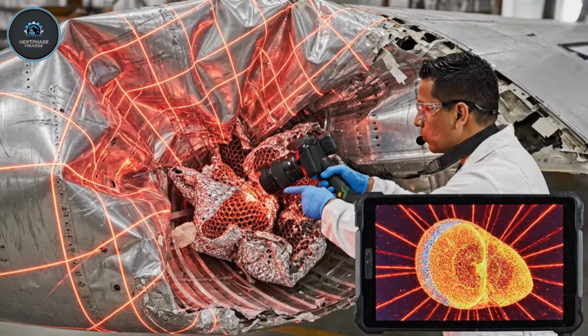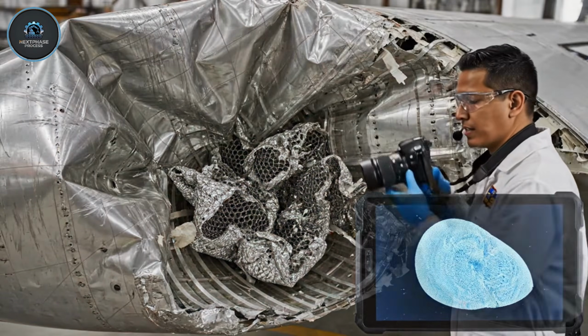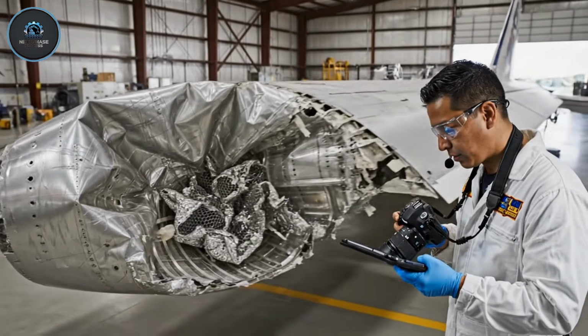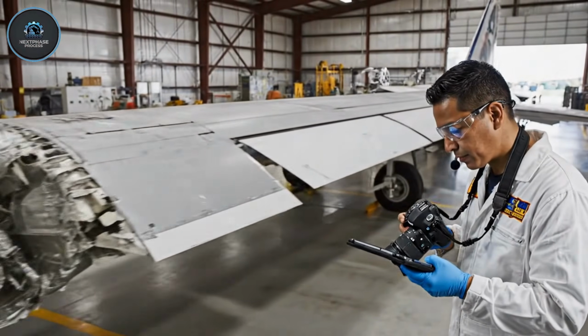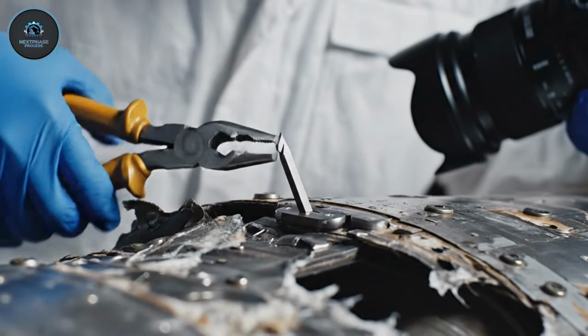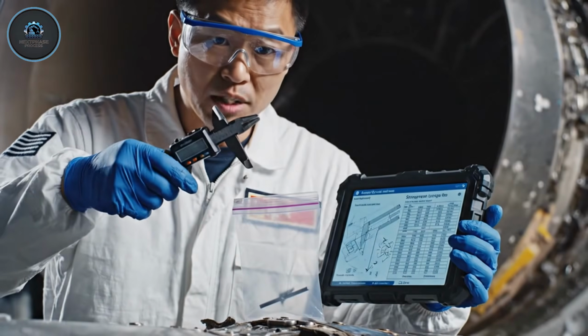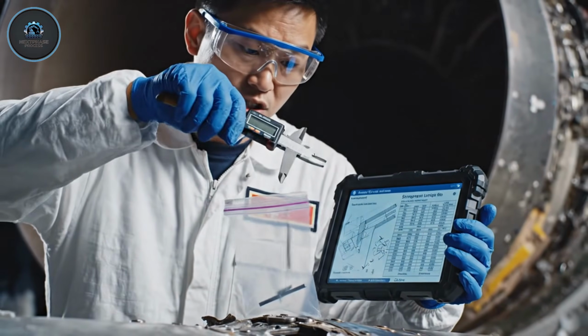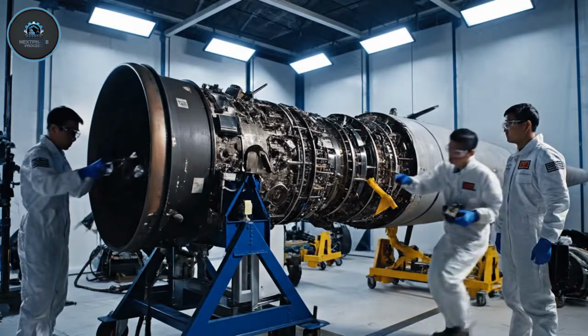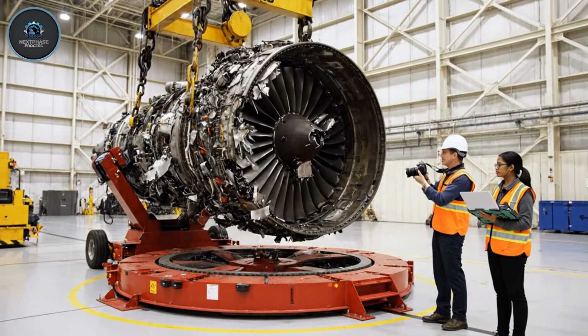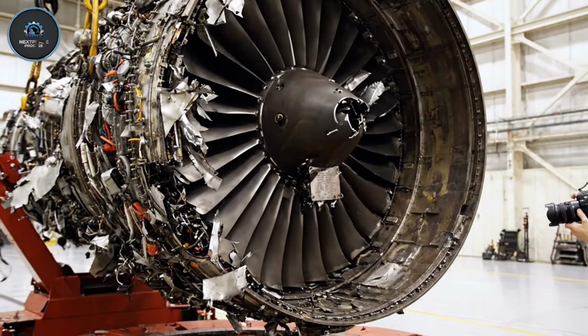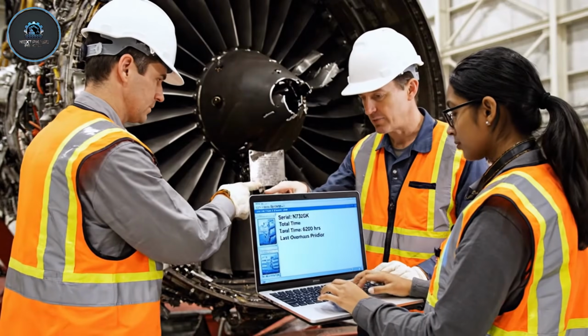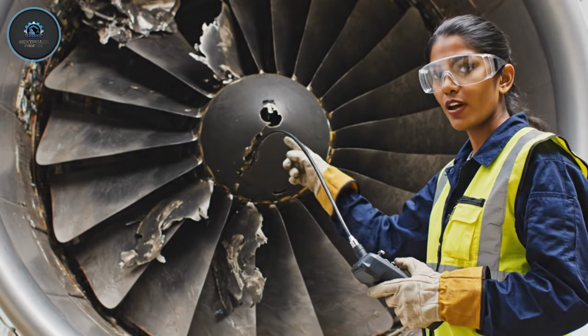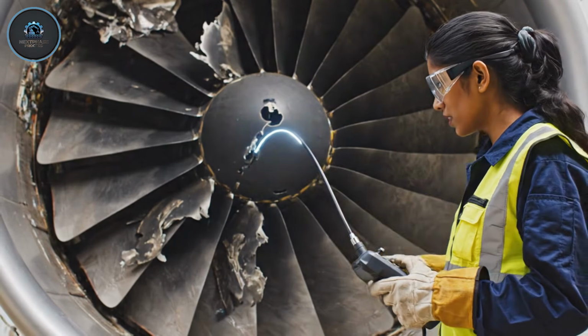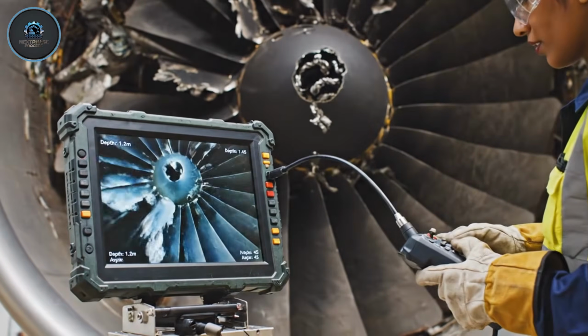Maximum crush depth 42 centimeters, located at station 375, consistent with approximately 30-degree impact angle. Pin diameter 8 millimeters, material specification 2024 aluminum, shear strength approximately 400 megapascals, gives us failure load around 45 kilonewtons. Serial number November 7, 32 Golf Kilo, total time 6,200 hours, last shop visit 14 months prior. Fan blade 7 shows forward bending, consistent with rotational impact.